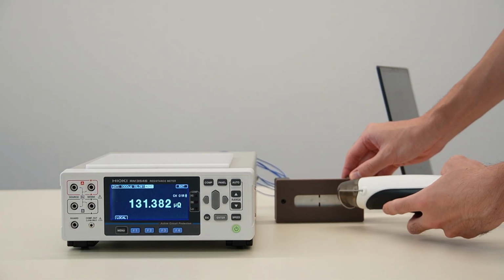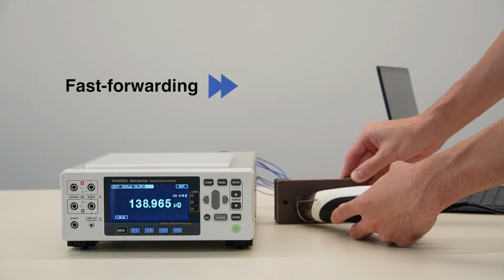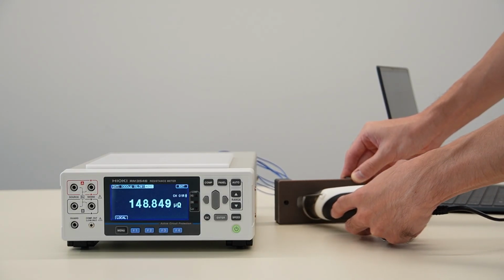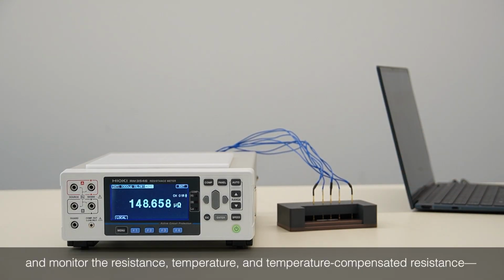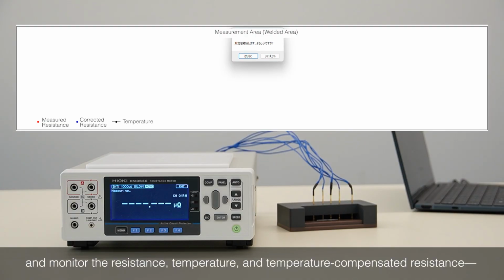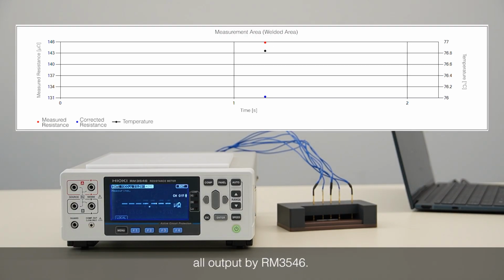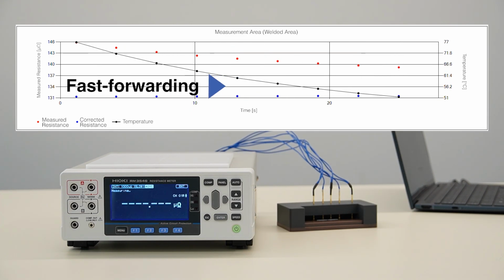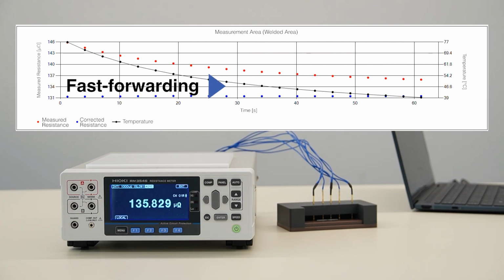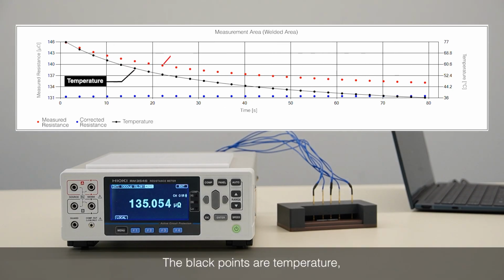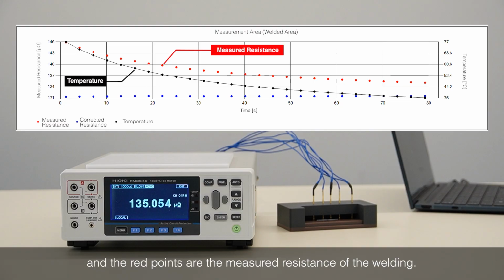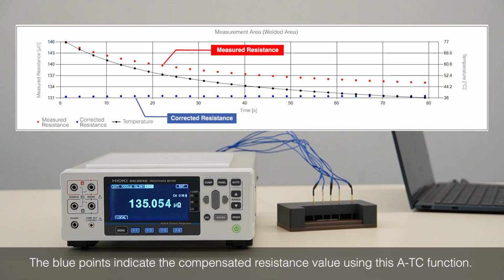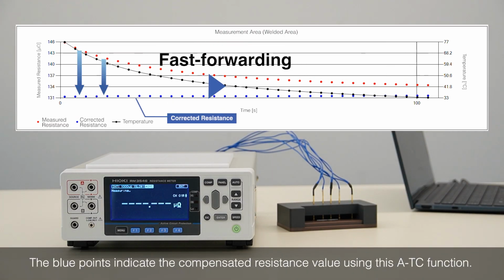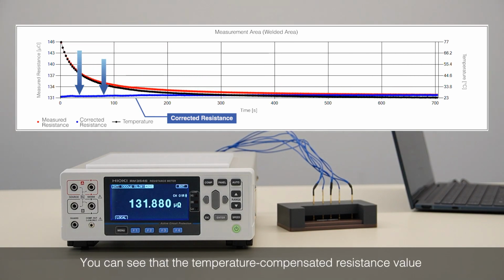We will heat the sample sheet and monitor the resistance, temperature, and temperature-compensated resistance, all output by the RM3546. The black points are temperature, and the red points are the measured resistance of the welding. Once the heat gun is removed, the sample starts to cool, causing both temperature and resistance to fall. The blue points indicate the compensated resistance value using this ATC function. You can see that the temperature compensated resistance value is unaffected by the temperature change.